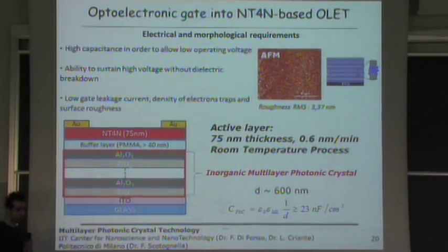Now, let's skip to the other modification we implemented to the device: the photonic crystal gate dielectric into the structure of the OLET. Here, the electrical and morphological requirements are rather stringent. We need high capacitance, ability to sustain high voltage, low gate leakage current, low density of electron traps, and low surface roughness. The surface roughness is good in comparison to the standard PMMA.